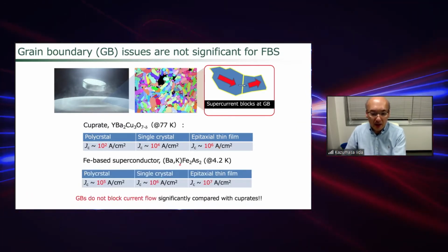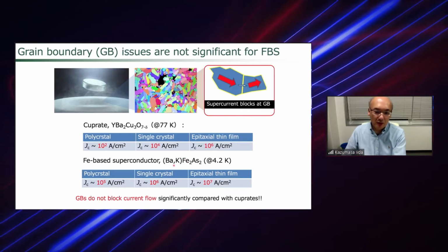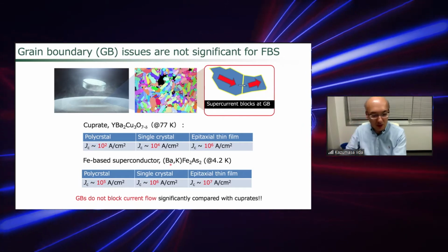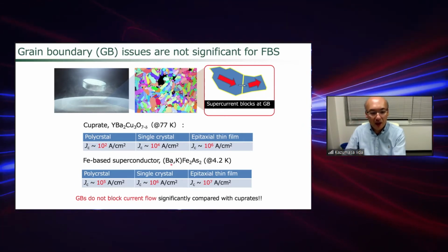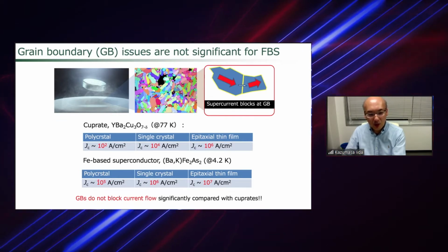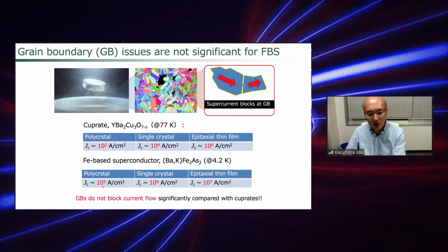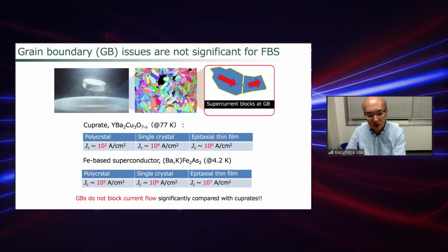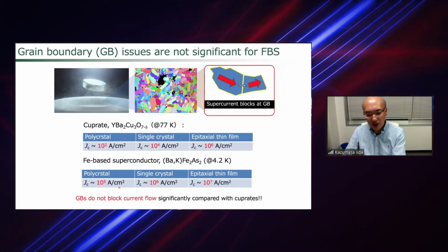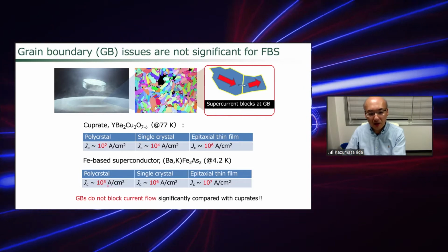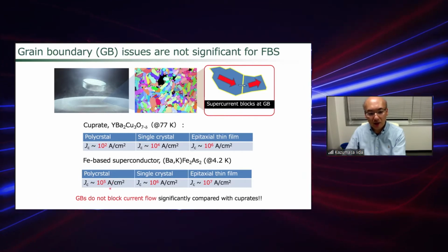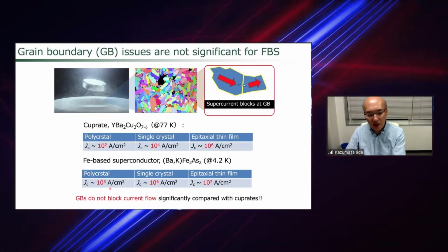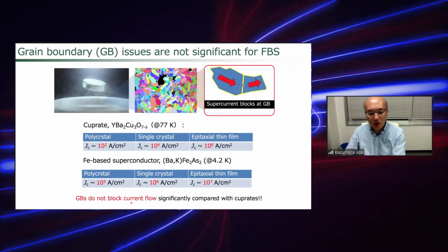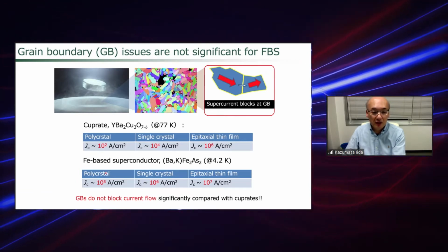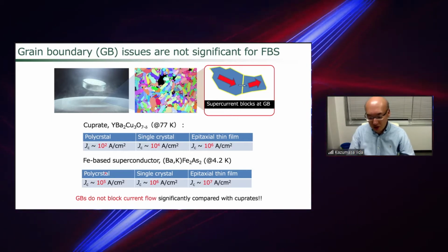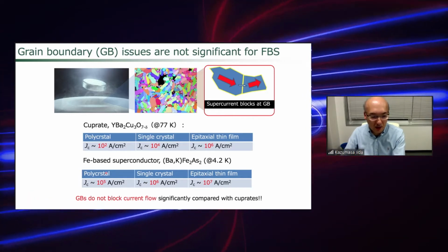On the other hand, for the iron-based superconductors, for example, this is potassium-doped barium 122, which is the most important material for applications. These materials in polycrystalline form show a Jc of 10 to the power of 5 amperes per square centimeter. Although this material also has weak-link behavior, the critical current density is quite high compared to the cuprate superconductors. So basically, the grain boundary does not block supercurrent flow compared to the cuprates. This is one of the reasons why we are interested in iron-based superconductors.